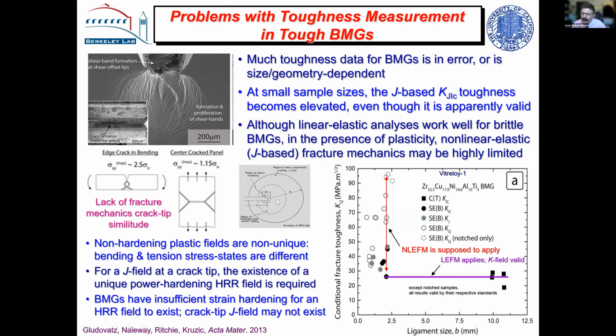But of course, these metallic glasses don't have any hardening. They soften. The shear bands are softening. So we think that one of the problems here is that the extent of the HRR field in a metallic glass is extremely small. So the region over which J can be a unique parameter would be highly limited.